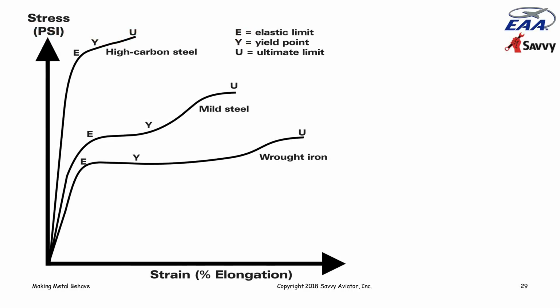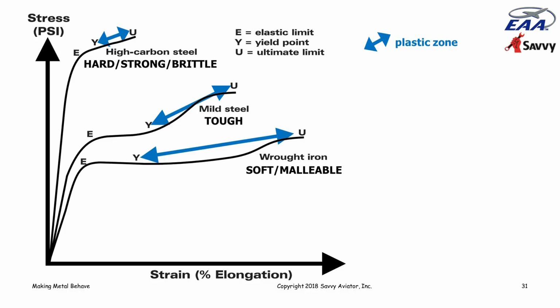If we look at a stress strain diagram for wrought iron, mild steel, and high carbon steel, you can see how it reflects the different characteristics of these different alloys. The first thing that's most obvious is that as you add more carbon to the alloy, Young's modulus gets higher, the material gets a lot stiffer, a lot harder. The slope of the proportional part of the curve gets steeper and steeper as you add more carbon, which means that the material becomes less and less flexible. But also the zone beyond the yield point, the plastic zone, becomes smaller and smaller as you add more carbon to the alloy. And what that basically means is that the material gets more and more brittle.